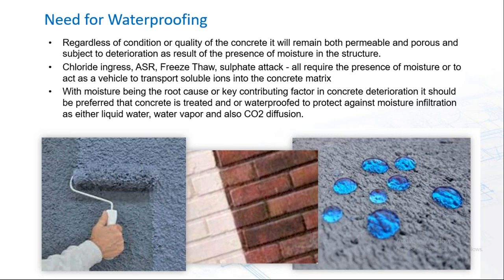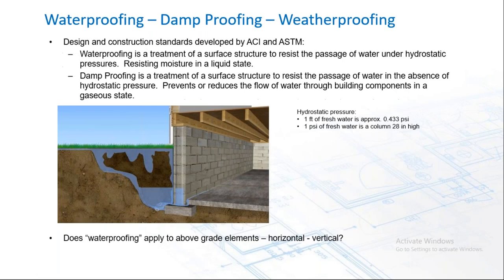Chloride ingress, ASR, freeze thaw, sulfate attack, they all require the presence of moisture to act as a vehicle to transport soluble ions into the concrete matrix. With moisture being the root cause or key contributing factor to concrete deterioration, in my view, it should be preferred that concrete is treated or waterproofed to protect against that moisture infiltration, either as liquid water, water vapor, and also protect against CO2 diffusion.